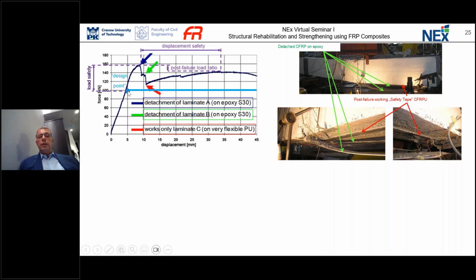So it is clearly visible on this graph. When we design the structure, we have some kind of design point. Over this design point, we try not to go because we have some kind of coefficient of safety. But if we have, for example, an earthquake, it doesn't respect our coefficients. And in this case, at the ultimate failure, the 2 epoxy resin systems suddenly failed, and everything was hanging on this 1 carbon fiber on very flexible polyurethane. This deflection that we can observe is still under the service limit state, because the service limit state was 12.5 millimeters.